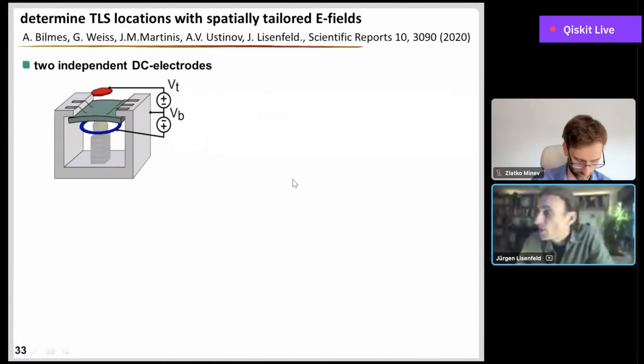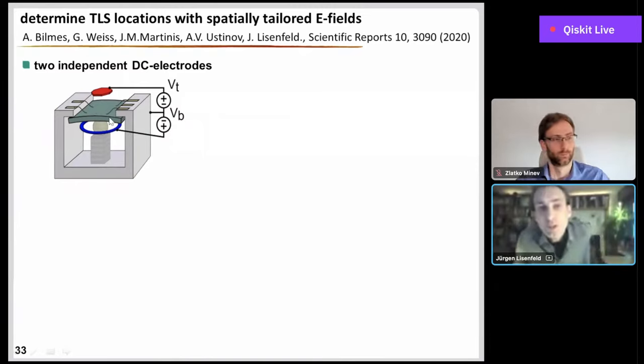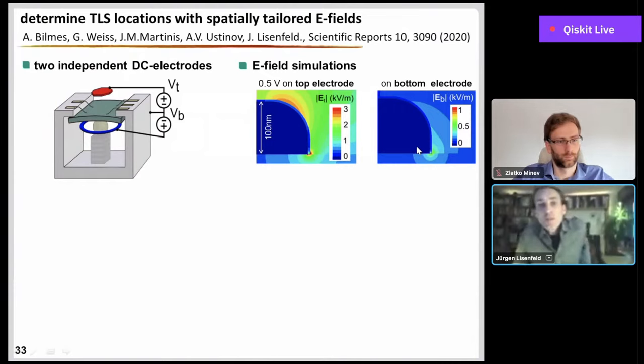Okay, so the last thing I would like to mention quickly is that we can also, again, go back to this electric field tuning, but get more out of it if you connect these electrodes separately to dedicated voltage sources, which are both referenced to the on-chip ground. And now you can imagine these two electrodes will generate very different field distributions in your chip. This is an example when you put half a volt on the top electrode. You see this top electrode mostly focuses the active field here on the top of the electrode, while the bottom electrode naturally just focuses more on the bottom here.